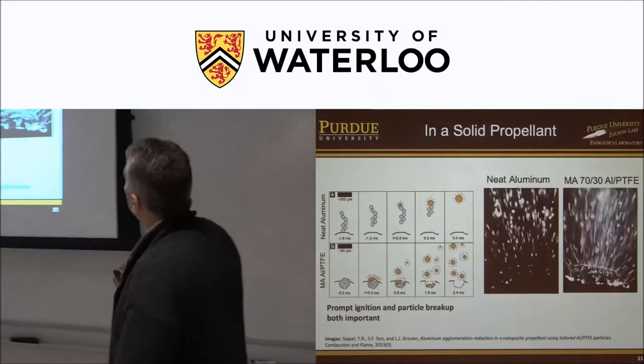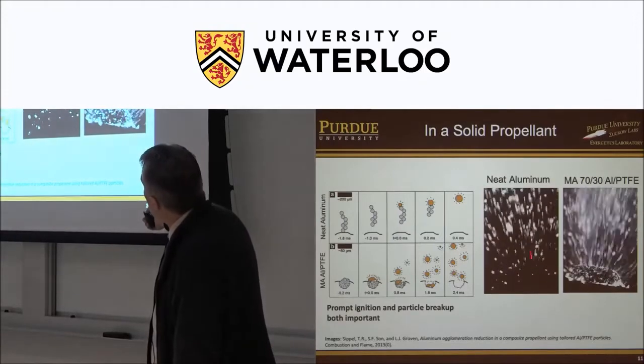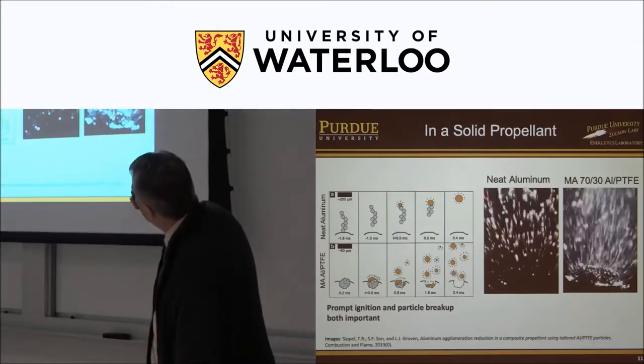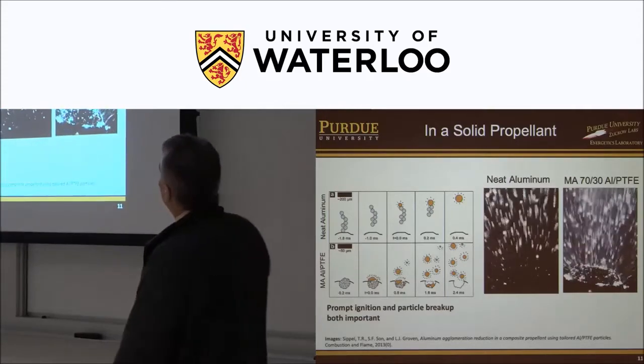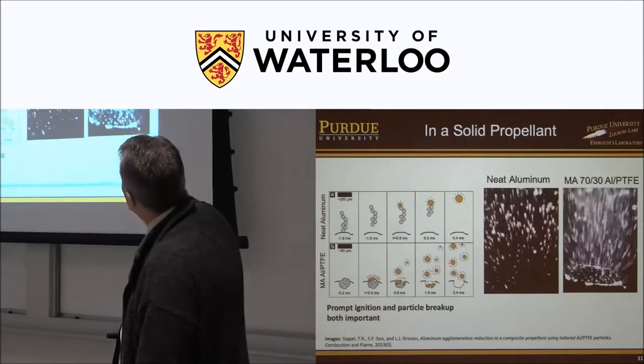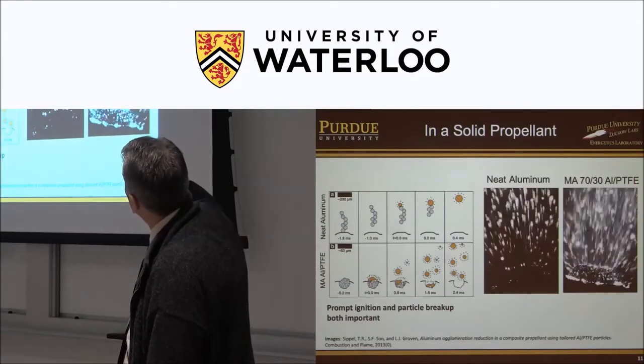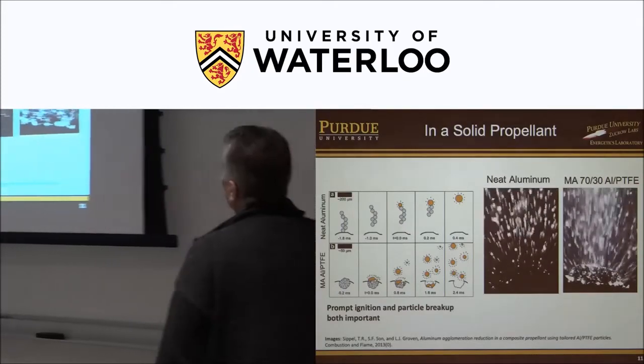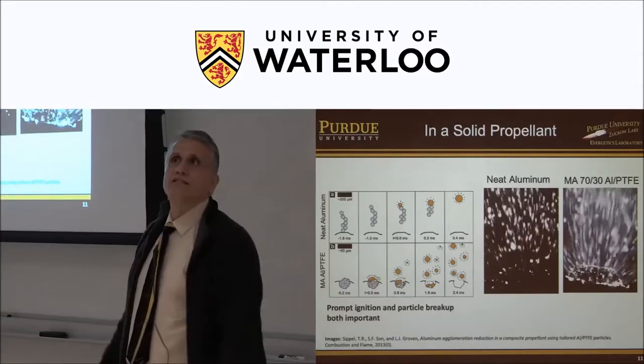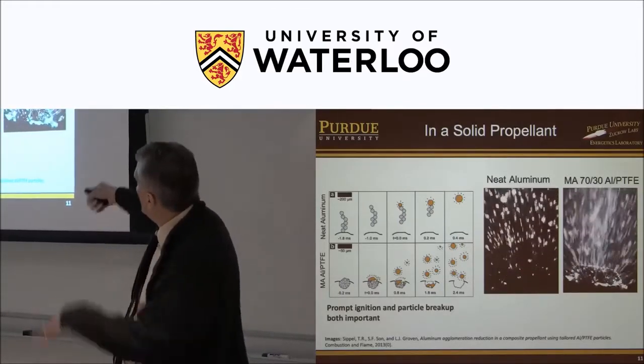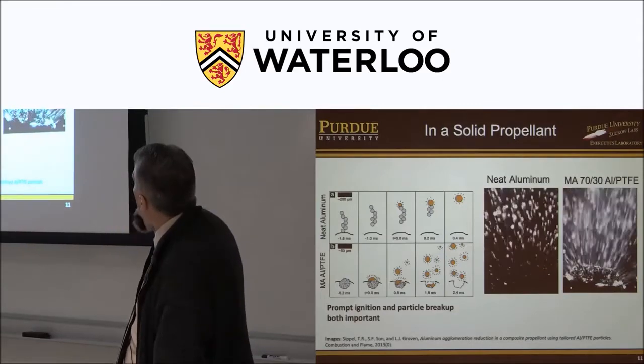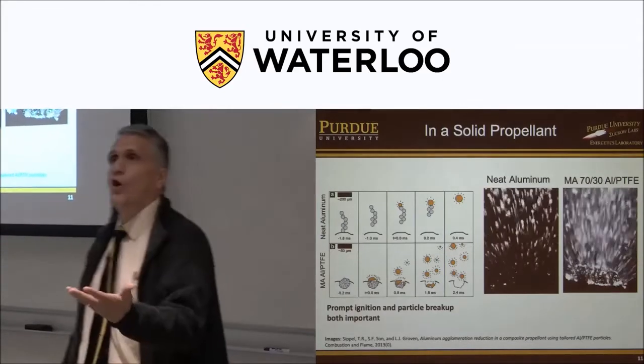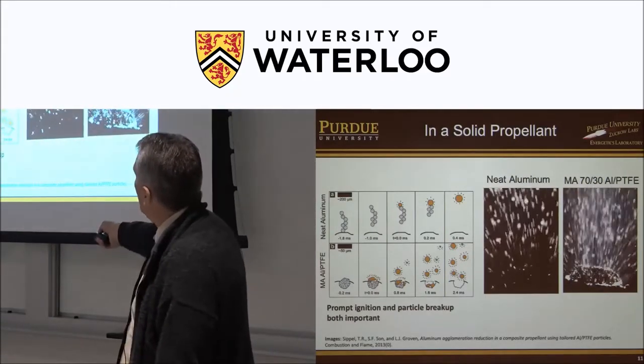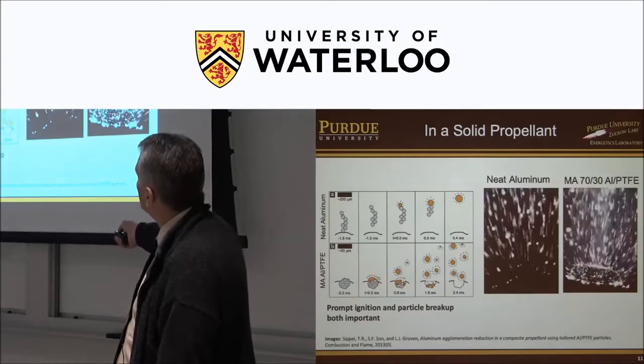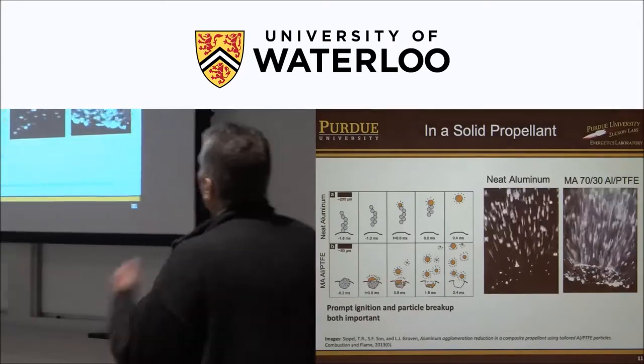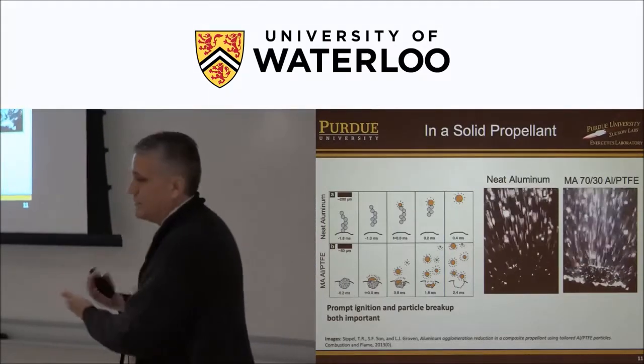this is the baseline aluminized propellant. This is the surface, if you look closely here. You can see these particles. Some of these particles you can see tails. That's alumina smoke coming off from that particle. And this is what we call mechanically activated 70-30, so 70% aluminum, 30% PTFE or Teflon. If you look at the surface, there's a lot more bright spots. It's igniting right at the surface rather than as it regresses down and then ignites. And you also see a lot more streaking. That means they're small particles. So what's happened is these composite particles ignite more readily at the surface, break apart into smaller particles, and that's, like I said, it'll improve the burning rate.